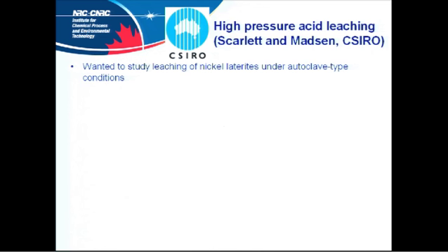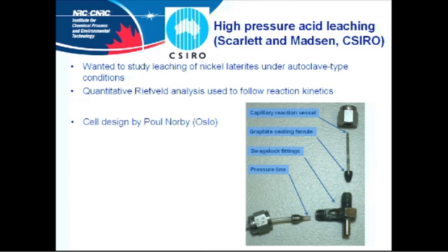This is some work by Ian Madsen, so I'm not doing all my own stuff. This is leaching of nickel laterites under autoclave conditions. So again, this is pressure. Want to use quantitative Rietveld analysis to follow reaction kinetics. This is basically designed by Paul Norby. This has been used on the synchrotron a number of times. And basically, it's a capillary reaction vessel.